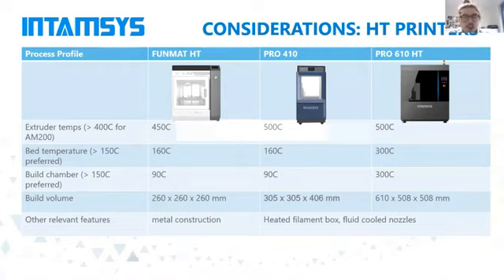Now I would like to give you a short introduction to our printer portfolio. So we have high temperature printers, starting with the FunMat HT, which is a really desktop-based high temperature printer with already a 90-degree heated build chamber. Then we have a Pro 410, which is a more industrial build machine with a dual extruder printhead, a water-cooled printhead, preheating filament chamber, and a lot of very good accessories. And then on top we have the Pro 610 HT with a 300-degree chamber, which allows you to print parts with AM200 directly in the crystalline state, which allows you to avoid annealing and avoid a lot of time in post-processing.